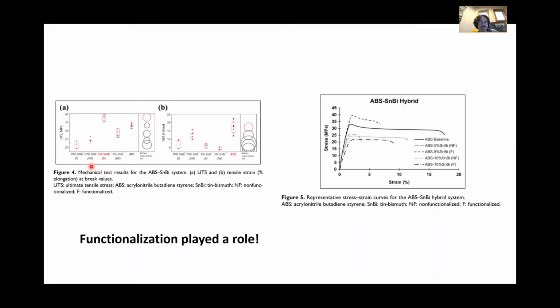We had a sweet spot in terms of composition. Putting in 10% by weight tin bismuth was too much, but 5% actually showed a strength increase. We see that both in our Tukey-Kramer graphs and our stress strain curves. We also see that ABS on its own was actually pretty elastic, with maybe 18% elongation.